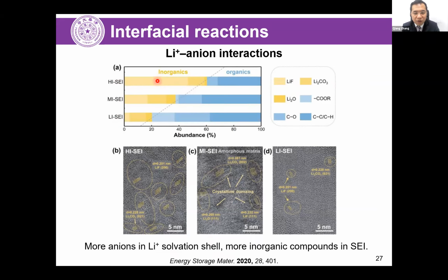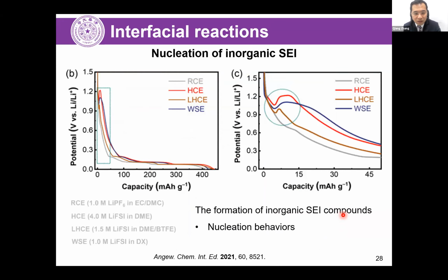The contribution of lithium fluoride, lithium carbonates, and lithium oxide was increased significantly. And this is also easily confirmed by the TEM observation, in which a lot of inorganic crystals can be found on the surface, while for the SEI in the low concentration electrolyte, it is found that there are many amorphous structures on the surface. So this indicates the ion-solvent complex structure can regulate the SEI composition.